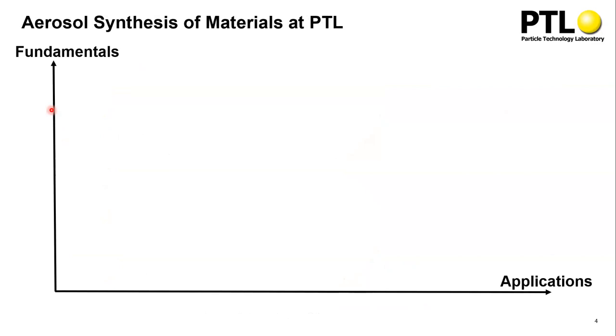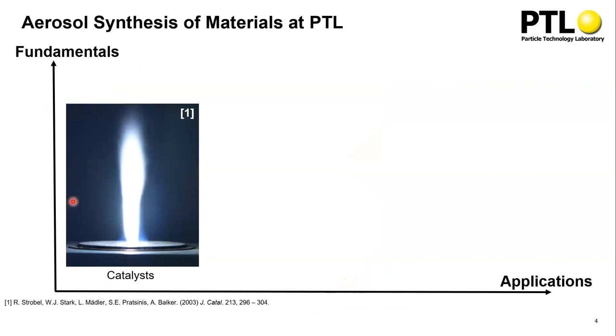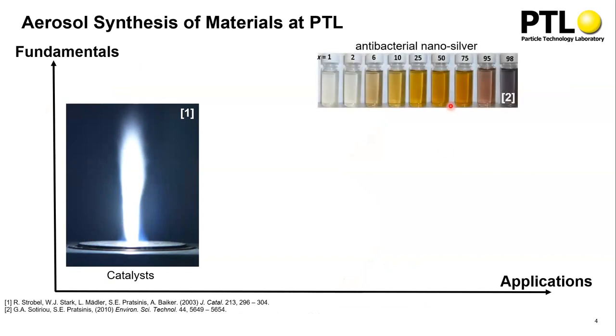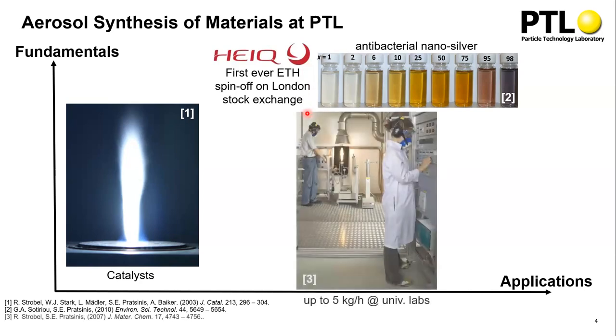In the lab, we also do experimental work, and a lot of work has been done on the flame synthesis of inorganic nanomaterials, specifically, for example, in catalysis, also with antibacterial nanosilver. And this in particular has spun off into a company, which was actually the first ever ETH spinoff to be listed on the London Stock Exchange, so it turned into quite a large company. And this was enabled by the fact that this flame spray process is able to be readily scaled up for industrial applications. In the laboratory, we've shown that we can do this up to 5 kilograms per hour. So by enabling these processes to be scalable, this can go out into real applications.